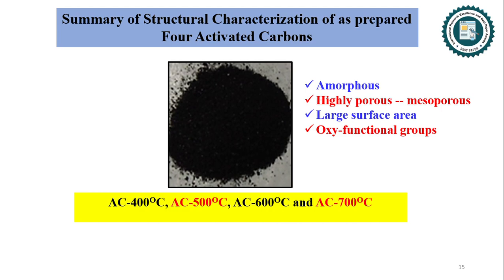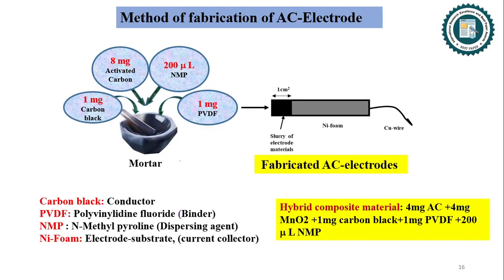Now, our focus shifted to fabricating activated carbon electrodes following structural characterization. Each electrode comprised 8 mg of activated carbon powder, 1 mg of carbon black, and 1 mg of polyvinylidene fluoride (PVDF) dispersed in 200 microliters of NMP solution. The resulting slurry was applied onto a nickel-foam substrate, dried overnight at 70 degrees and activated by immersion in a 6 molar KOH aqueous electrolyte solution.